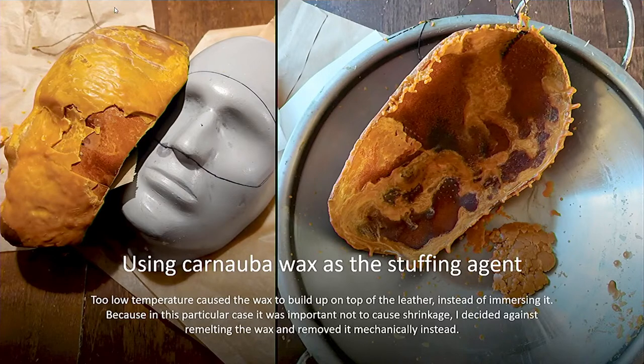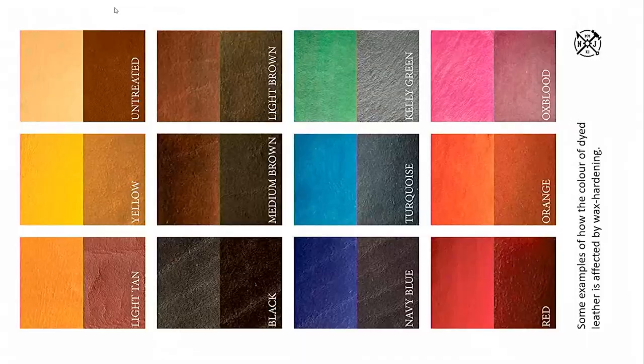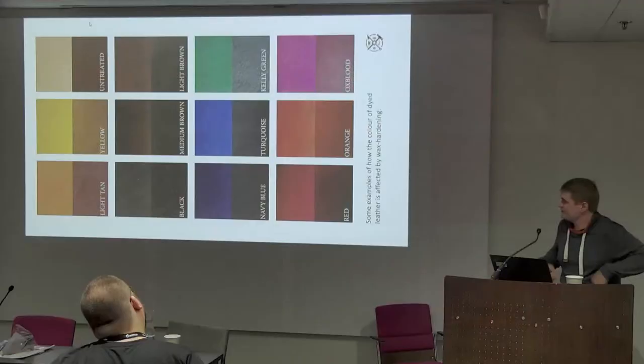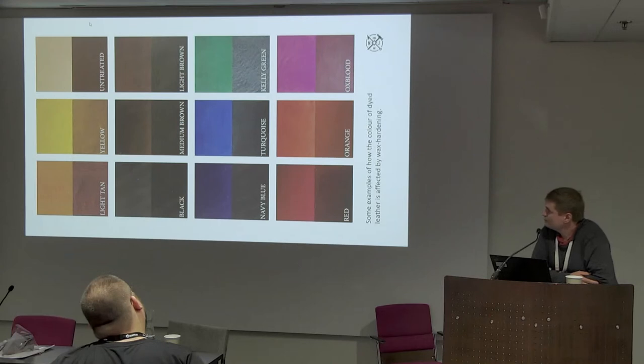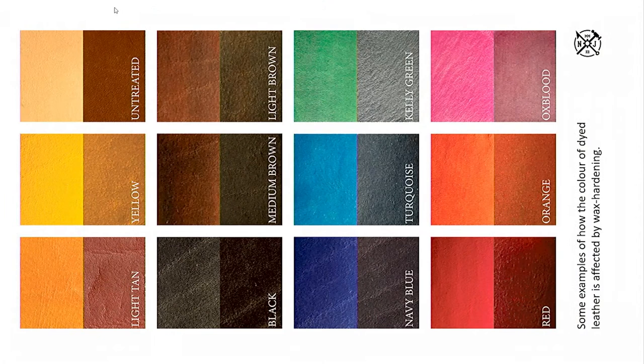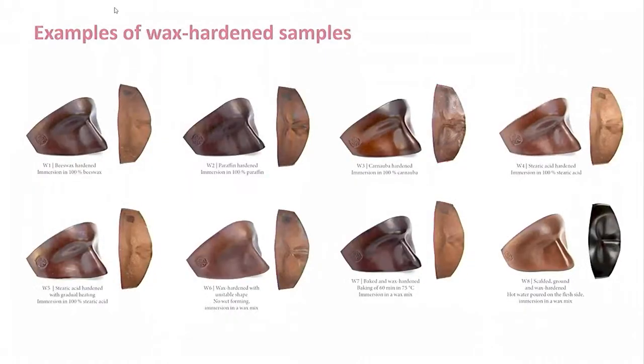And another thing, because dyeing leather is pretty common with wax hardened leather, is that wax hardening darkens the leather quite a lot. In the top left corner, you see completely undyed leather, and the other picture on the right is when it has been wax hardened. So you dye the leather and get all these nice colors, but you get a lot darker and many times not so nice colors out of wax hardening. So that's one thing to keep in mind when doing wax hardening. Okay. Then, yeah.